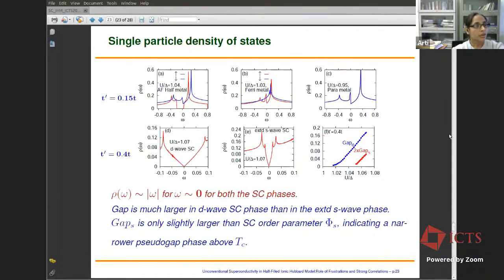Okay, so we also looked at the single particle density of states in all the metallic phases. As you can see, in all the metallic phases, whether it's a paramagnetic or a ferromagnetic metal, the density of states at the Fermi energy is very low and depleted, which is consistent with the fact that we had small Fermi pockets in these metallic phases, and these metallic phases are actually compensated metals.